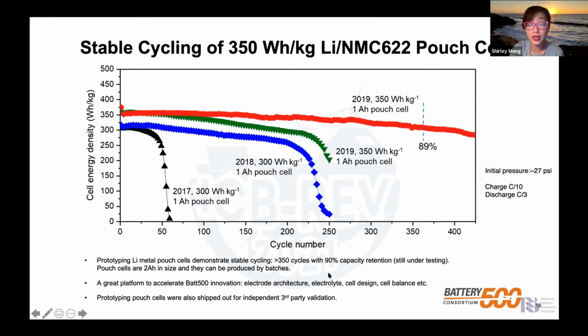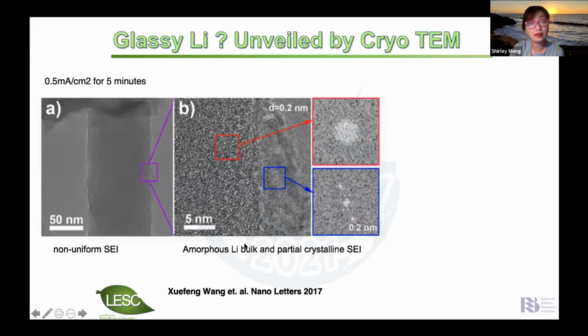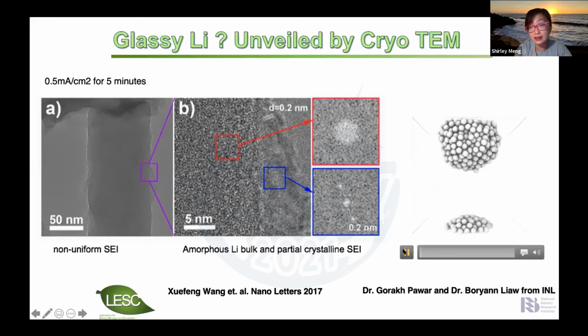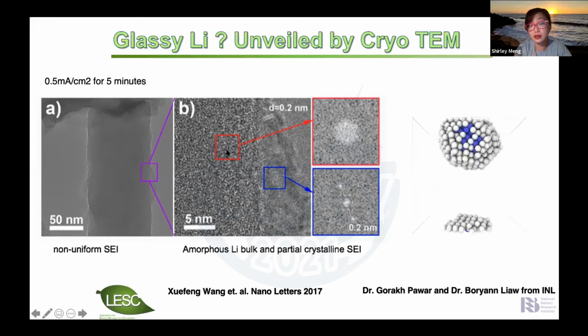So the fundamental knowledge we gained from studying the lithium metal anode really paid off. And actually, during this process, we discovered something very intriguing that has not previously been reported. When we look at the atomic resolution image of these first nucleated lithium, we actually saw a very, very disordered, almost glassy lithium. And this led to a series of very interesting theoretical studies to see why the lithium metal, the alkaline metal, has some very intriguing behaviors at the very beginning of nucleation. And that has a lot to do with the nucleation and the growth of lithium metal.